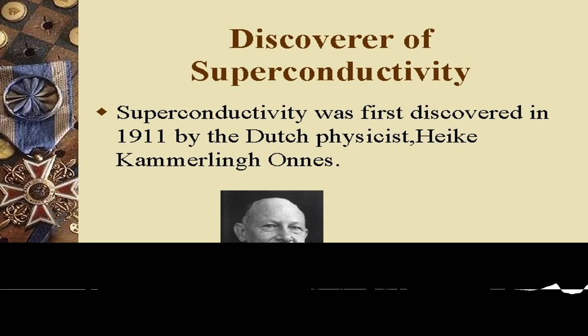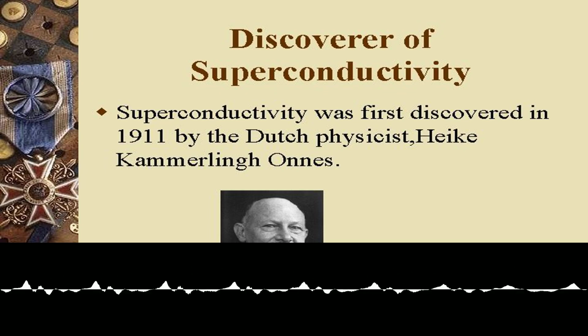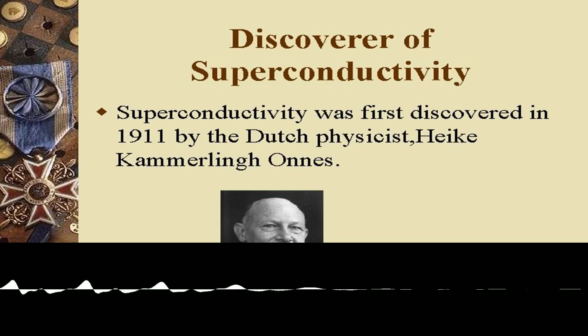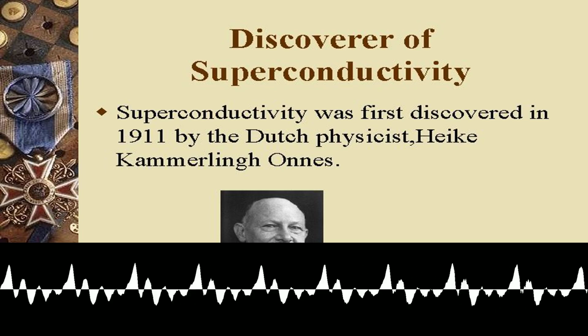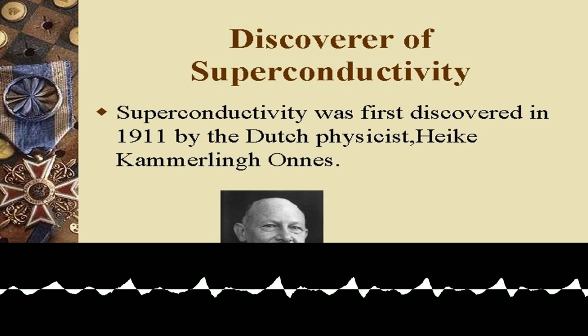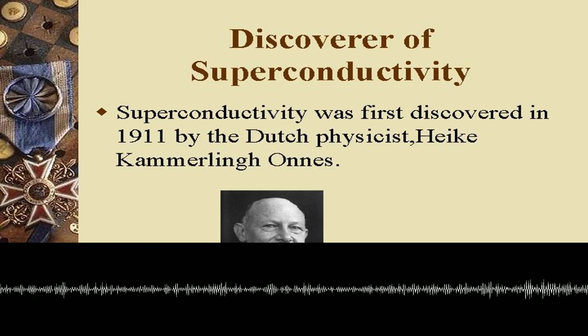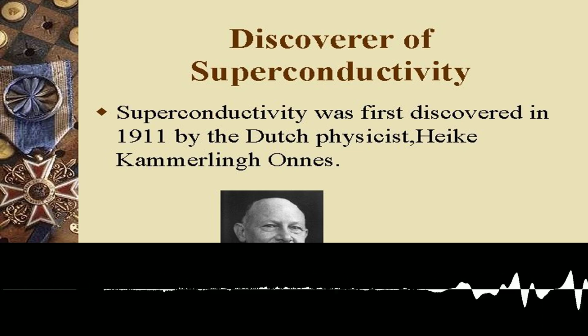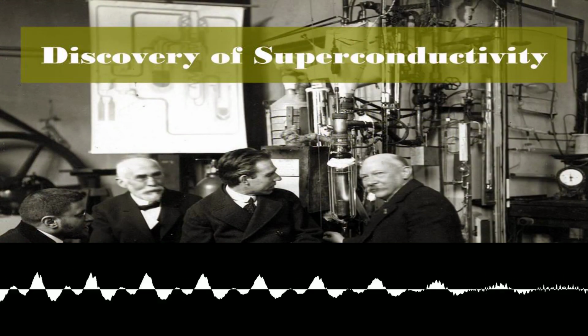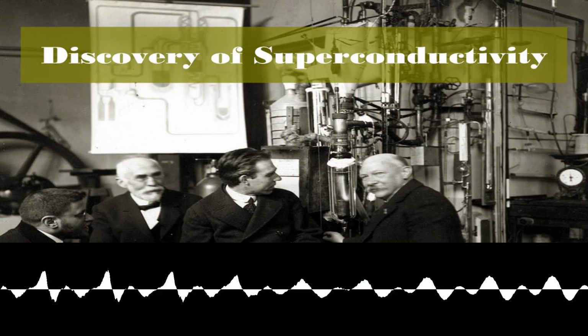This precision was a direct result of their unparalleled control over the helium bath's temperature by manipulating its vapor pressure. The work further extended this concept by examining the effects of material purity. They presented evidence that adding impurities, such as cadmium to the mercury, broadened the transition. This finding was crucial. It supported the argument that superconductivity was an intrinsic property of the ideal, pure material, and that the sharpness of the transition was a key feature of the underlying physics.